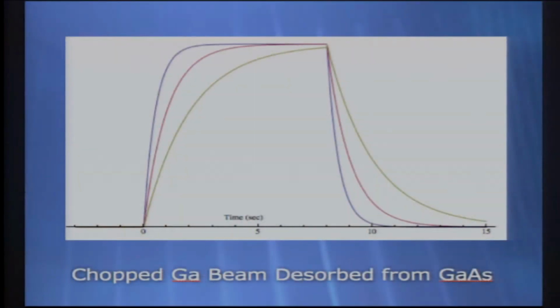And if we could, there it is, okay. That's just a mathematical depiction of what it looks like at 3 different temperatures. But it's a simple first-order differential equation. The solution is straightforward. You get a 1 minus exponential rise and an exponential tail. And that's exactly what we found with gallium on gallium arsenide. Furthermore, the enthalpy of vaporization, which you get from the temperature dependence of these curves, agreed exactly with what we'd already measured in the mass spectrometer experiments. So this was behaving perfectly normally.